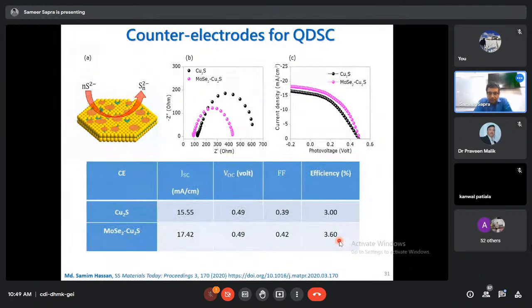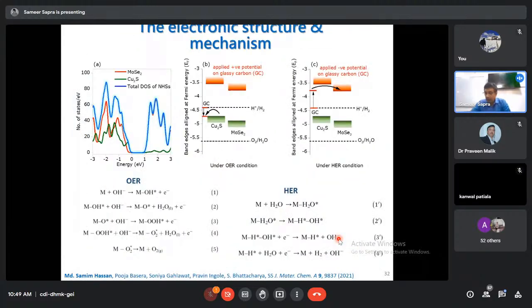All right, what else can one do? Well, you have these counter electrodes for dye-sensitized solar cells. You also have counter electrodes for quantum dot-sensitized solar cells, and those are cuprous sulfide. And we, Shamim, decided to use molybdenum selenide cuprous sulfide, hoping that it'll have much better charge carrier transport efficiency. And you know, QD solar cells with cadmium selenide do not give you very high efficiency, so don't worry about 3%. But the fact that it does increase because of the heterostructure is very interesting. What else can one do? Okay, and that is evident if you take a look again at these electronic structure calculations.